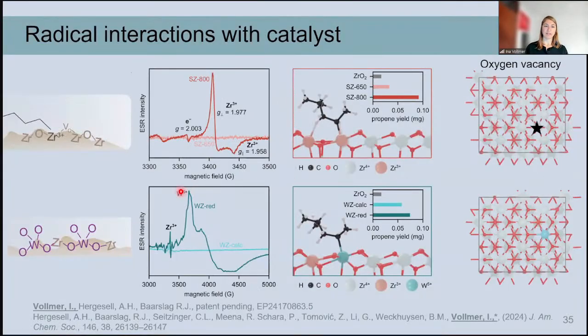So actually, this etching with the sulfuric acid is creating some surface roughness, which can also play a role, but most importantly, it creates these oxygen defects, and together with zirconium 3+, which can actually stabilize the radicals.